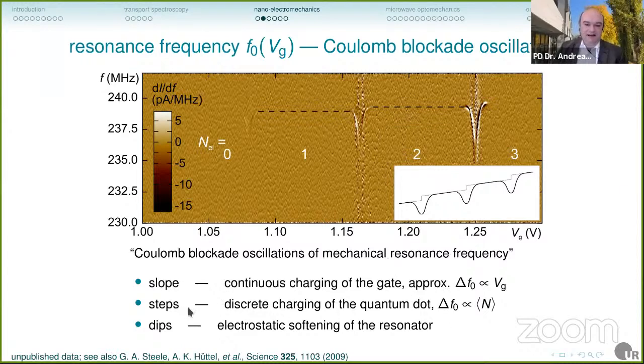The steps are the discrete charging of the nanotube, of the quantum dot. So at each of these Coulomb oscillations, you add 1 elementary charge, and that adds a discrete amount of pull, a discrete amount of mechanical tension, and thereby resonance frequency. And the dips, finally, correspond to so-called electrostatic softening of the resonator.